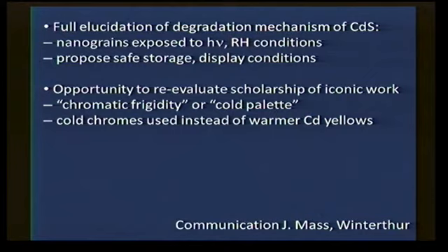If we do the analysis, use a synchrotron radiation beam, do the mapping, and look at the elemental composition, it's still cadmium yellow, but the cadmium yellow is transforming with time. There's a degradation process. So it's not so much that Matisse was using a different technique or different pigments. It's just that the initial pigments he was using degraded with time. So what we see now doesn't reflect how the painting was a few years back.